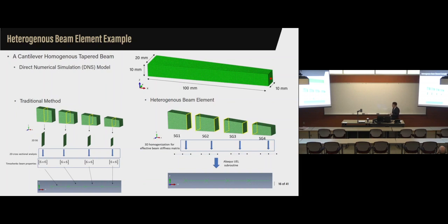And also another example is on the heterogeneous beam element. You can find out that we have a tapered beam. We made it homogeneous to be simple enough so that this is a DNS model. And we start from 20 millimeter to 10 millimeter. And there are two ways to do it. Traditional way, because when you're dealing with a tapered beam, you want to model it as a beam, you have a beam element, then you cut a few cross sections to get the corresponding beam stiffness to work for the beam analysis. And for our new method, basically we cut a segment or a brick, a block of the original 3D model. And for each model, we carry out our homogenization analysis, get the effective 18 by 18 element stiffness matrix to do the one-dimensional analysis here.